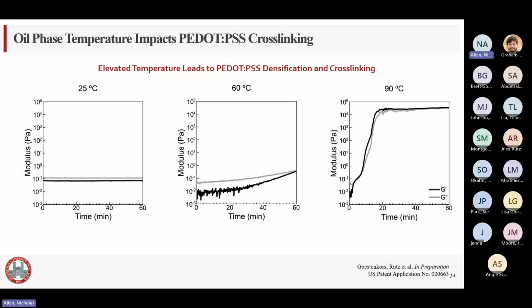So as you can see, at 25 degrees Celsius, the aqueous colloidal dispersion did not see any change in the loss or storage modulus. It was not indicative of any cross-linking taking place at room temperature at all. At 60 degrees Celsius, we saw an increase and it almost crossed over, but not quite. And at 90 degrees Celsius, we saw a crossover between the moduli at 3 minutes. So very fast cross-linking there. So from this, we learned that the PEDOT:PSS aqueous colloidal dispersion does experience cross-linking at elevated temperatures, albeit a little bit slower, obviously, at 60 degrees Celsius.